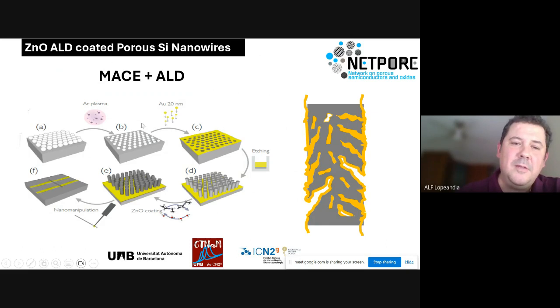They do this is not nanowire, this is polystyrene, and they do the deposition of metal, and then they do the etching, and the etching is preferential below the metal, leaving the nanowires on top. And these nanowires, while they have some residual gold in between, that enters into generating holes. And then the idea was, once we have the nanowires, the forest of nanowires, we can cover them with zinc